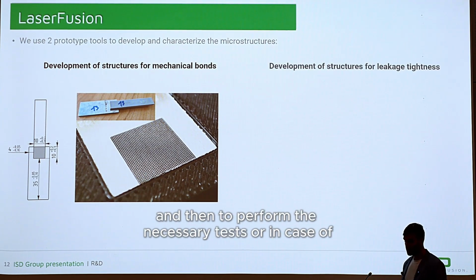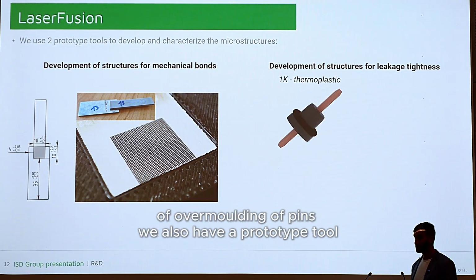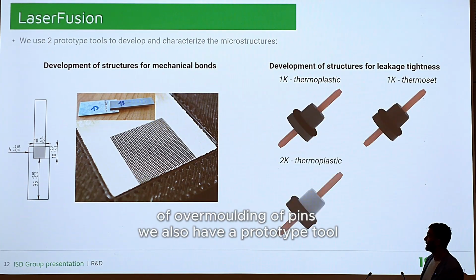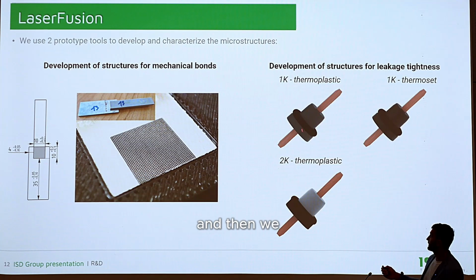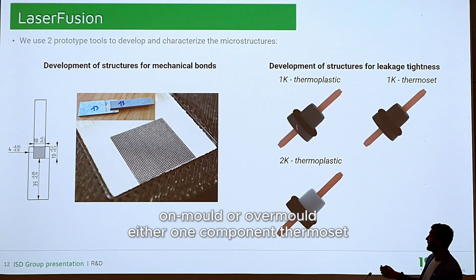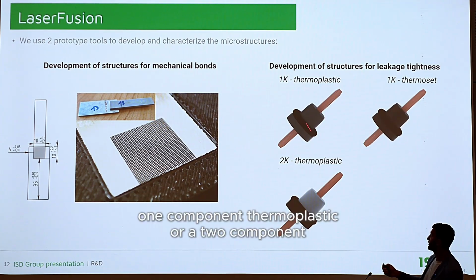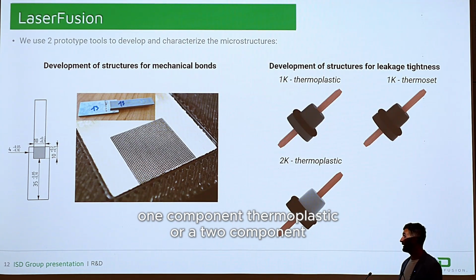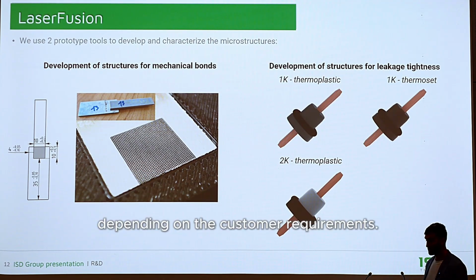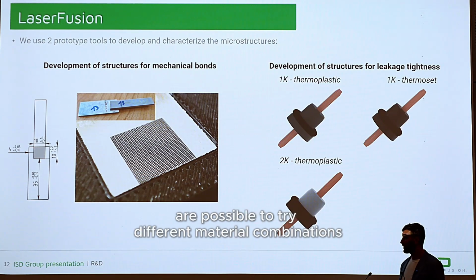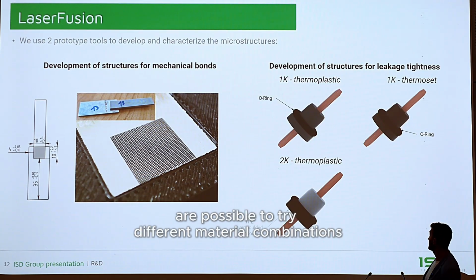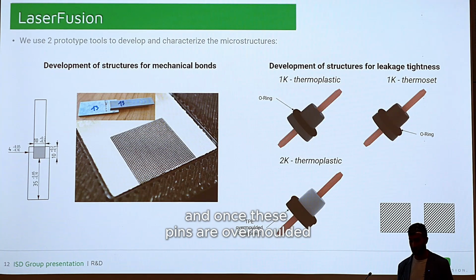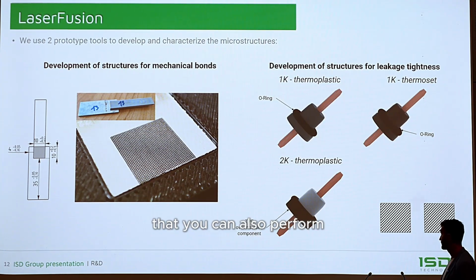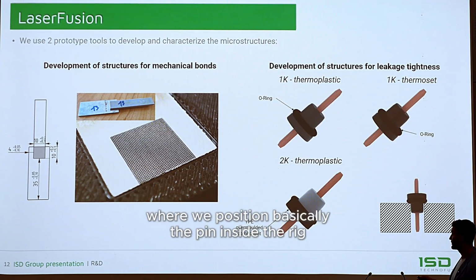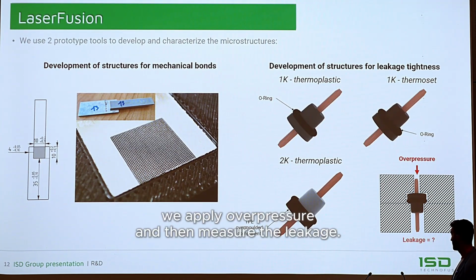Or in the case of overmolding of pins, we also have a prototype tool where we structure the pin and then we onmold or overmold either a one component thermoset, a one component thermoplastic, or a two component, depending on the customer requirements. So all these possibilities are available to try out different material combinations. And once these pins are overmolded, we can also perform a pressure test where we position the pin inside the rig, apply overpressure, and then measure the leakage.